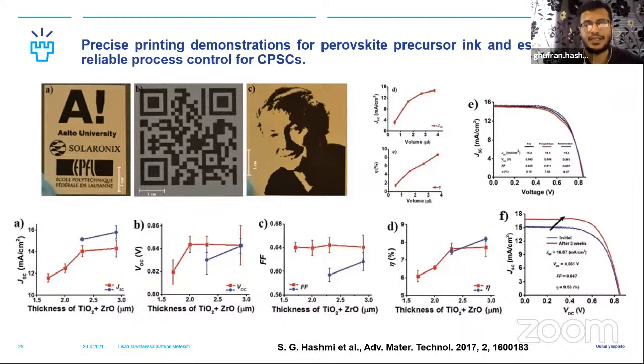But if you are not showing reliable process control, meaning that the materials you are using should be integrated with a controlled volume or in a reproducible fashion in order to achieve high reproducibility. And this we proved in one case with the perovskite cells, where all the other layers of this monolithic device design of the perovskite cell were done with scalable techniques like screen printing, except for the manual infiltration of perovskite. And what was happening was that the performance reproducibility was getting compromised, meaning that we were not having reproducible efficiencies among the fabricated batches.